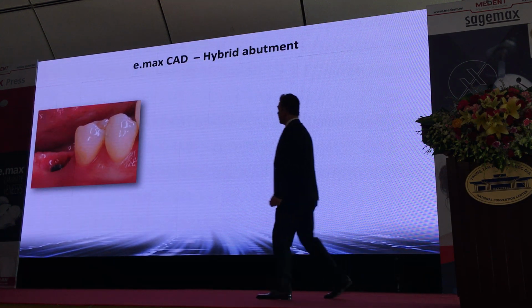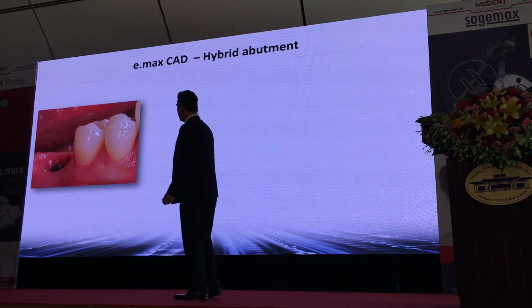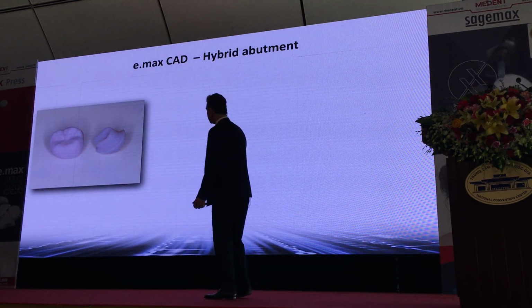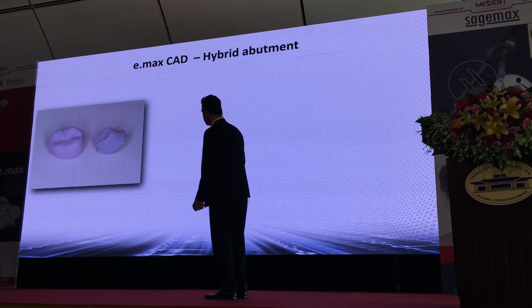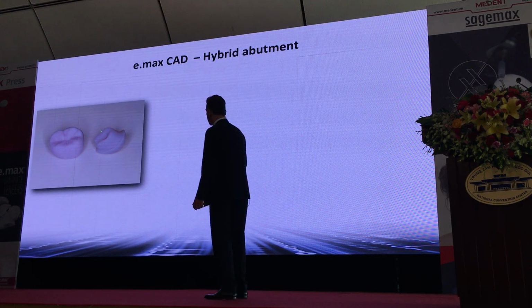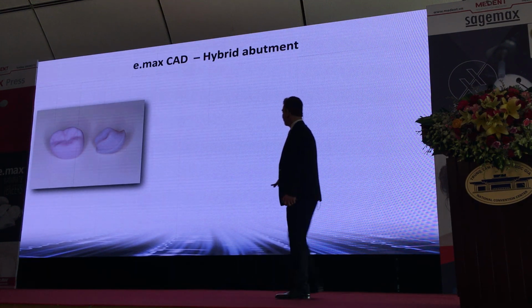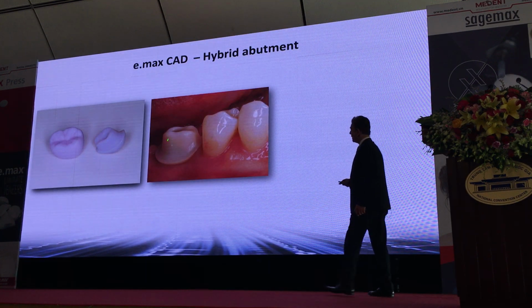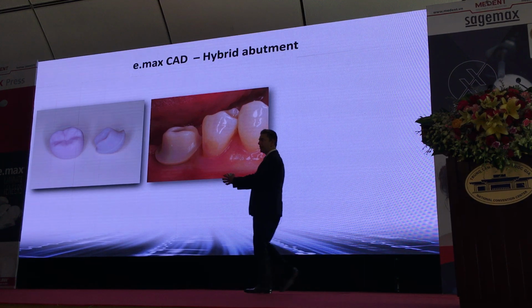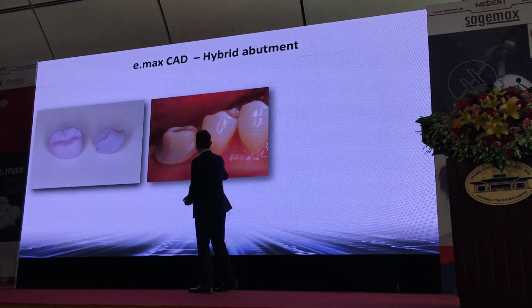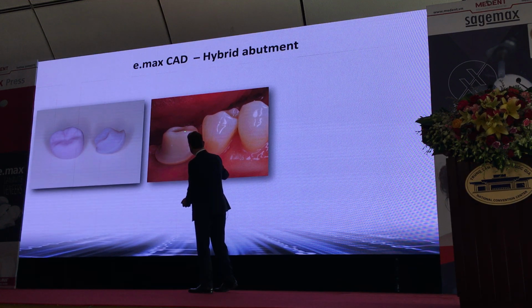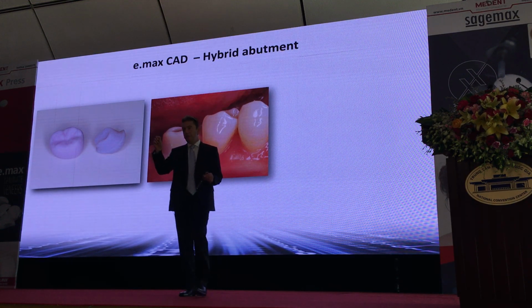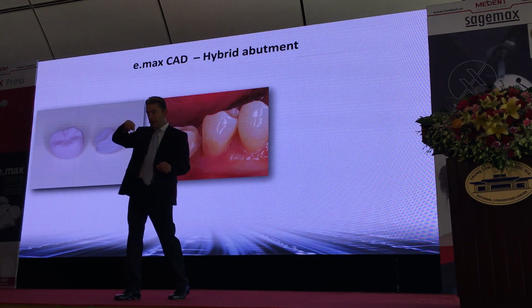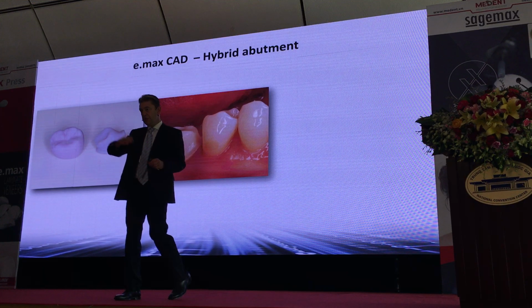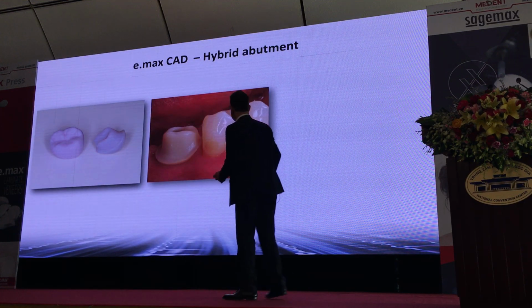Okay, so now this is a clinical case. You can see here the abutment, the implant. And in this case, this one is the abutment that has been produced and milled with emax. And this will be the crown, which will be later on cemented onto the abutment. Okay, now you can see here the abutment is already done, is already screw retained on the implant. And now on top of this, this access hole here will be closed. You can use a little bit of Teflon tape first in the deeper area, and then we will use some composite to close it.